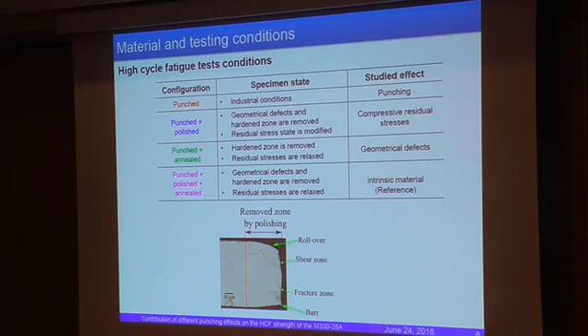Most important, we used 4 different configurations in order to uncouple the different effects. First configuration are punched specimens. So we use the very same conditions as industrial punching in order to assess the resistance of our material. But we also polished some specimens in order to remove both the geometrical defects on the edges and the hardened zone. And this polishing, as you can imagine, also introduces compressive residual stresses, as we will measure later.